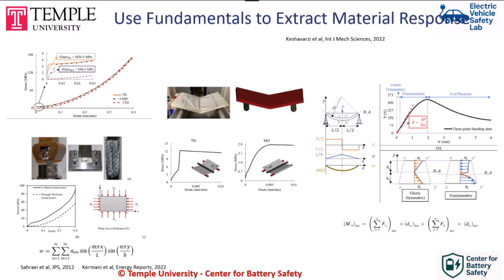Even if you do that, if you take it out of the casing, out of the electrolyte and the winding, then the behavior will be different. So the way we have figured out to calibrate it, we do bending tests. Because we know the compression part of the behavior, and we have to have equilibrium of moments and force equilibrium, we extract the tensile part of the curve by writing a code that takes into account the force displacement and takes out the compressive part.